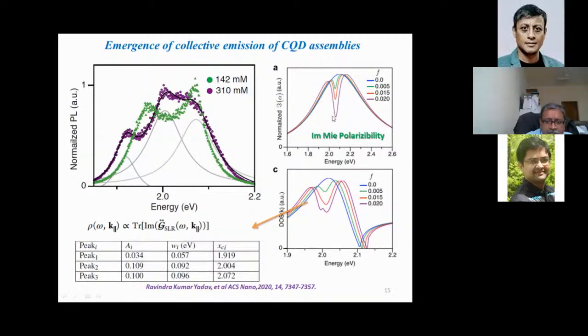So essentially, we then look at the modeling of this in terms of an effective medium picture, right? And the effective medium is in terms of the quantum dot, and this represents the concentration. As you increase the concentration, this increases the oscillator strength, and as you increase that, you start seeing this strong splitting in the imaginary part of the polarizability. There's a small detail in the analysis: these are taken as spheres for simplicity, but I guess the results would hold good, although the actual shape of these particles is disc-like. So you can see that scaling.